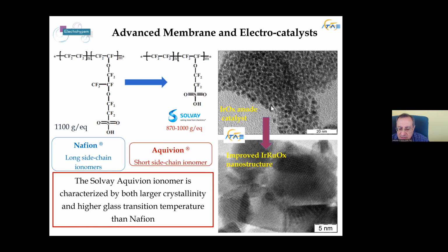When we started, about 15 years ago, to study electrolysis, we were focusing on nano-sized amorphous iridium oxide nanoparticles for the anode. After several years, we realized that the crystallographic structure plays a relevant role, meaning intrinsic activity is extremely important, and we need specific crystallographic orientation.